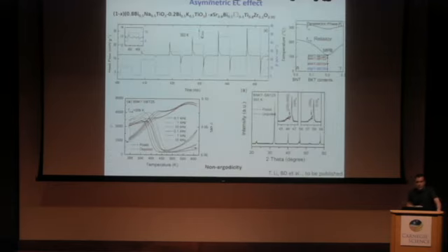What we can have also, we can have some asymmetry effect. For instance, in case of this system, we measure, you see, we apply the electric field here, then we have delta T increasing. This is a conventional electrocaloric effect. But when you switch off, we have delta T negative, but the amplitude is not the same. In a normal system, the amplitude for positive and negative, it's exactly the same. Here, the main reason of that is because we are playing with a non-ergodic system. And depending how you go toward this ferroelectric phase, you will not have exactly the same thing. So this is something that we can also use, having a delta T positive bigger than a delta T negative. And we can think to a way to design a device with this mechanism.